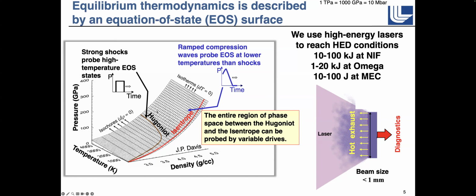We use high energy lasers. We use what's called an ablation process where you shine a high energy laser on a material, and you turn the surface of that material into plasma, which then jets out back toward the laser and forms essentially a jet. So it's essentially the rocket equation. And as you know, for driving a spaceship, you'd prefer to have low Z exhaust that you throw out. It's more efficient. And so we tend to use low Z materials as our ablators.